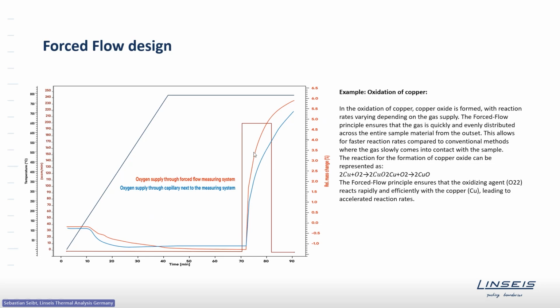The orange one shows a little bit faster mass increase than the blue one, and the reason is that the orange one shows the forced flow technique. So here the oxygen directly was put through the crucible, while in the blue one, the standard default design was used, where the oxygen was released next to the sample-containing crucible. So you see the reaction rate of the orange one is faster, and there's a faster response, and the sample is reacting much faster and more completely than if you release the gas next to it. So that's just a test we did to show that the system really has a huge influence on the reaction rate and the reaction control of any sample.